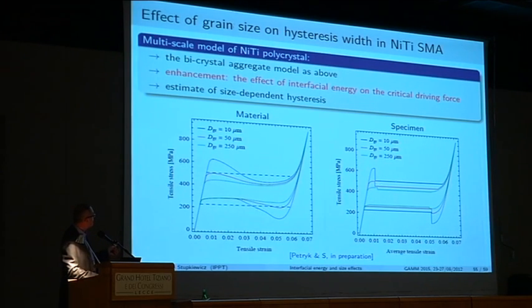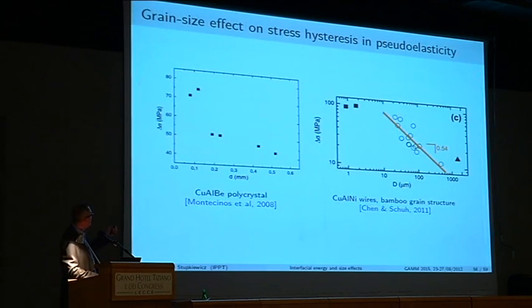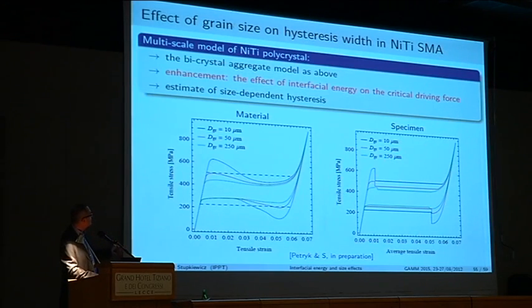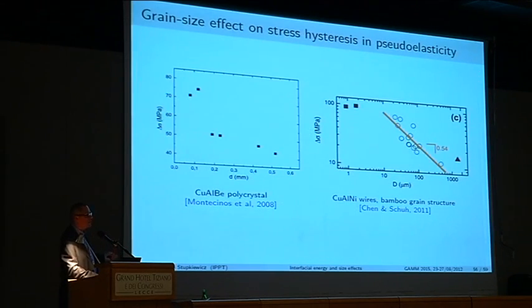Anyway, again, what we have here is that the dissipated energy, which is the area of this hysteresis loop, does depend on the grain size, and it actually increases with decreasing grain size. There are not many results in the literature on that, but those that are available show exactly the same trend: with decreasing grain size, you have increasing energy dissipation. So qualitatively, we represent these effects by our modeling.